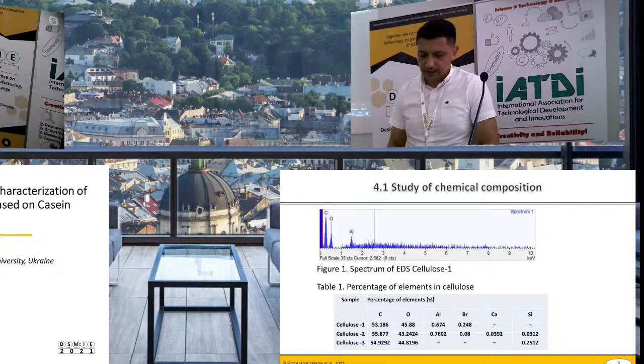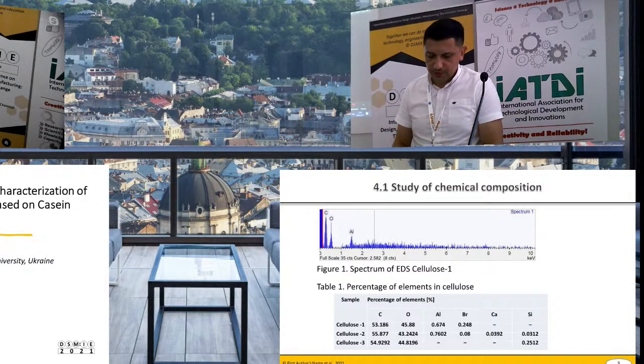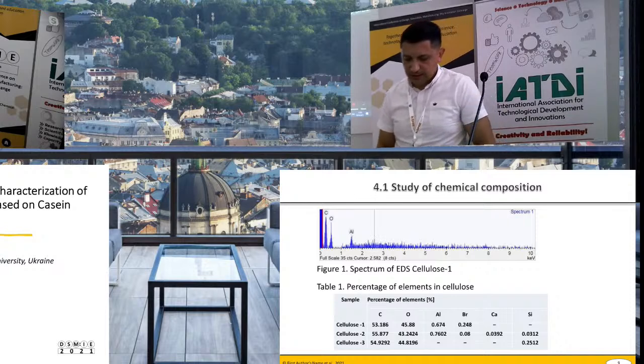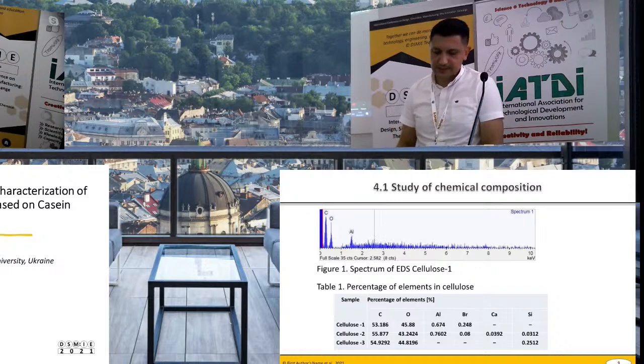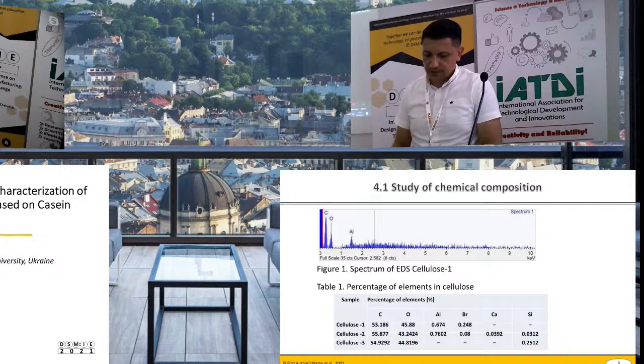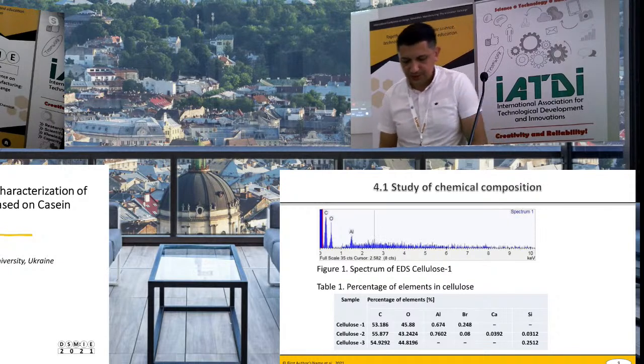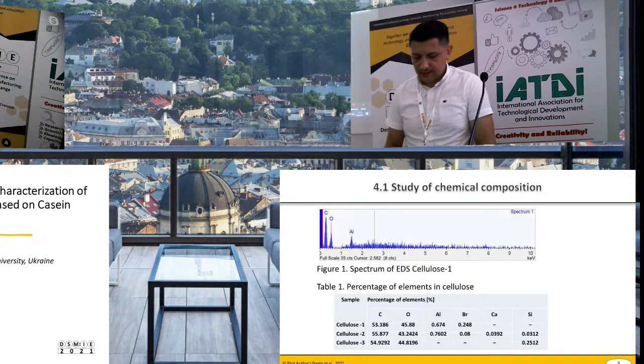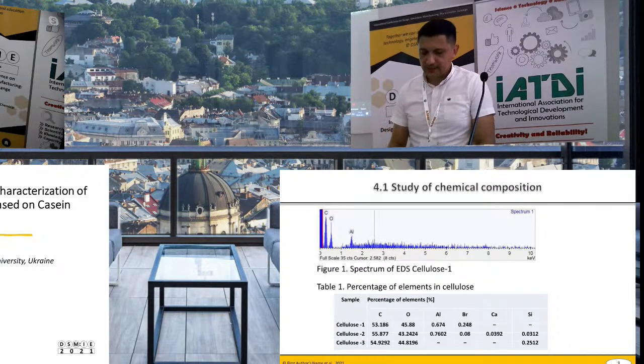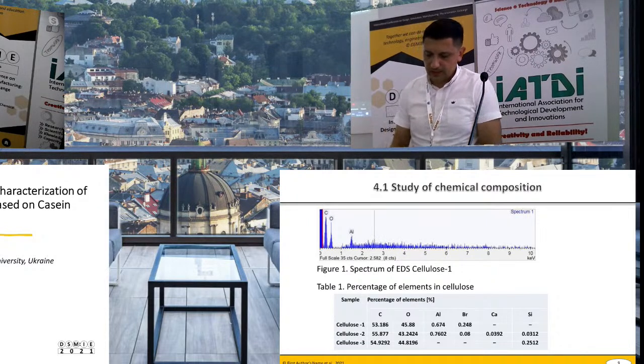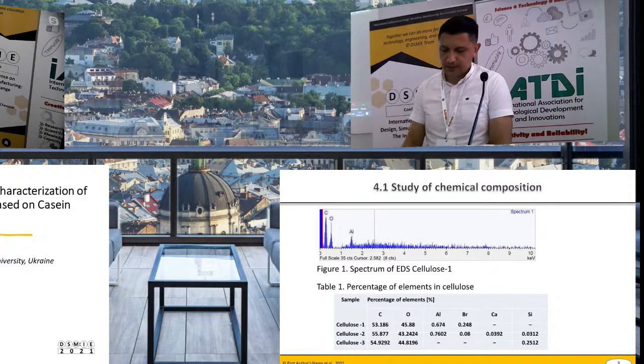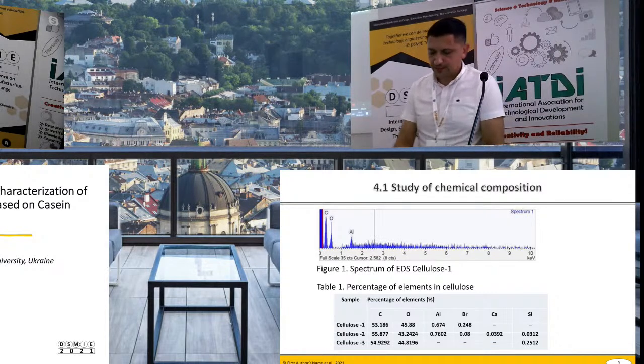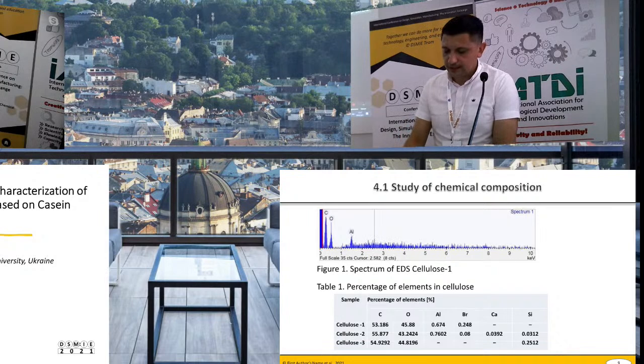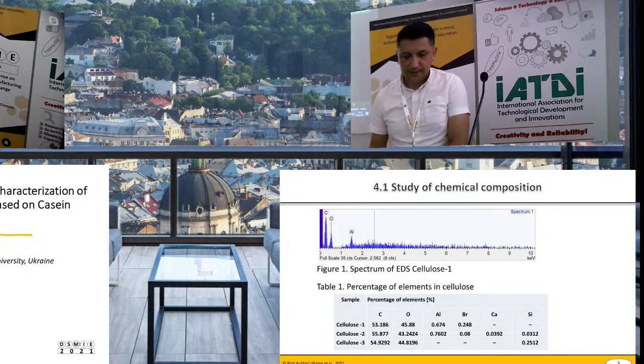According to the research, cellulose contained mostly carbon, about 55%, and oxygen. Cellulose also contains hydrogen, but due to its atomic mass being less than these elements, it is impossible to detect it during the study of chemical composition. The results show a small number of elements such as aluminum, bromine, calcium, silicon. Their presence can be explained by contamination resulting from contact with the holder and with the test samples placed. The result of the study shows that the 3 types of cellulose obtained don't contain harmful elements and heavy metals. Please, next slide.